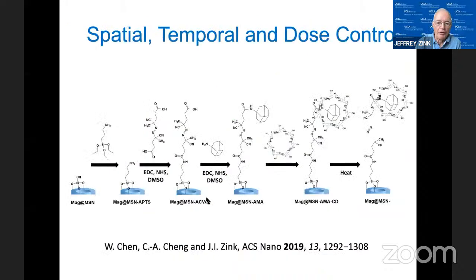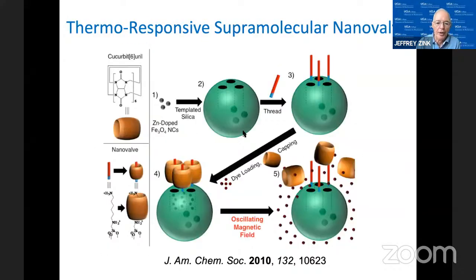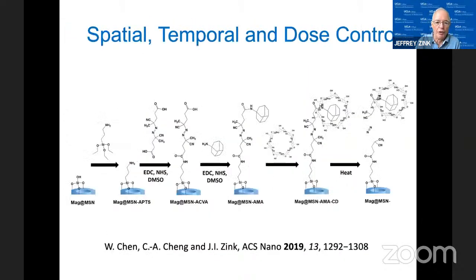And in this particular system, I should go back once if I can. In this particular system, we were able to do this in ice water. So we were able to show that without any external heating at all, just that internal heating, we could release the cap. So that was a test to show that we have control as we wish over the release of the drug.